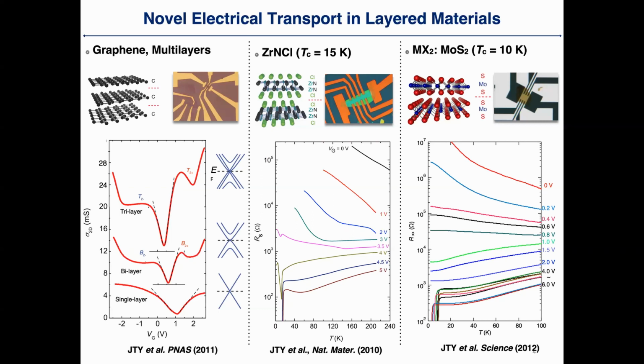And using this same technique, you can also apply it to layered materials and induce superconductivity. The typical device is very similar to the previous cartoon. You apply a gate bias between the channel and a gate electrode somewhere over here. Then you can induce carriers onto the channel and drive the system into the superconducting state. This worked many years ago already, in 2010 in zirconium nitride chloride, and later on we could induce superconductivity in molybdenum disulfide.